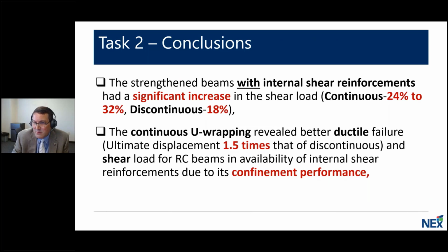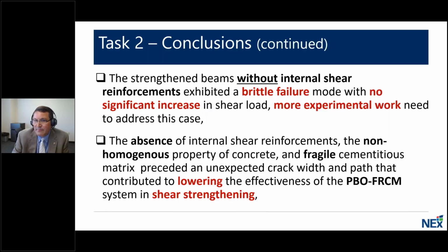So for shear, the strengthened beams with internal shear reinforcement had a significant increase. For the continuous FRCM, it was 24 to 32%. For the discontinuous strips, it was only as much as 18%. The continuous U-wrapping revealed better ductility though, 1.5 times that of the discontinuous strips, as we saw in the figures. The strengthened beams without internal shear reinforcement exhibited a more brittle failure mode with no significant increase in shear load, although, as I said, probably more experimental work is needed to understand and address this case scenario.